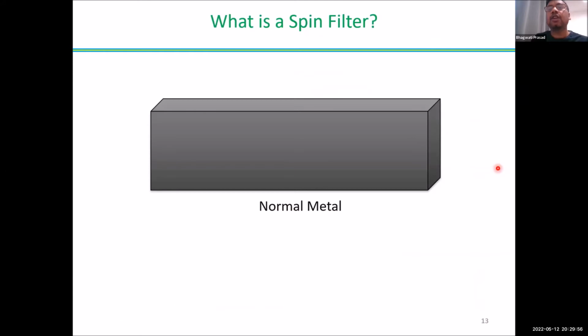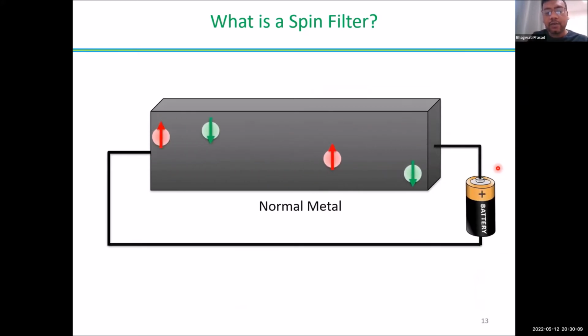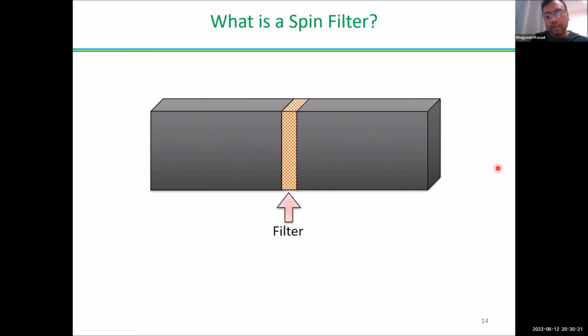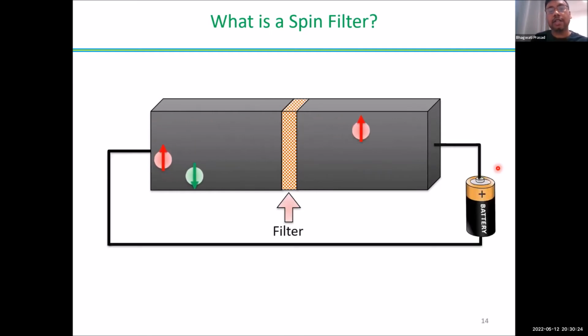One of the means is something called a spin filter, where you filter one direction of spin and only allow the other direction of spin to pass through. Let me explain a little bit how it works from this illustration. If you have a normal metal and you apply an electric field across it, irrespective of the spin orientation, the electrons will accelerate toward the positive bias. But now imagine a situation where you have some sort of filter that allows only one direction of the electron spin to pass through and completely blocks the other direction. Then on this side you can have highly spin polarized current. Okay, so the aim is to get 100% spin polarized current on this side.